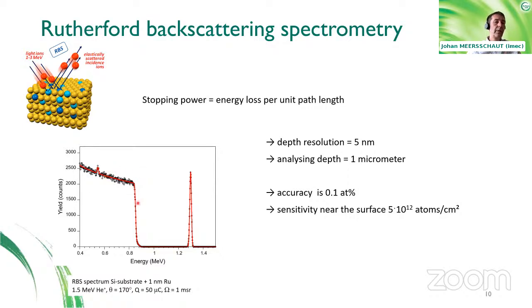The depth resolution can be quoted as the resolution with which you can measure the energy differences. And in practice, this is of the order of 1 nanometer. The full analysis depth is twice the penetration depth. And this is of the order of 1 micrometer for practical applications. And the accuracy is of the order of 0.1 atomic percent. And near the surface, we have a sensitivity of 10 to the 12 atoms per square centimeter.